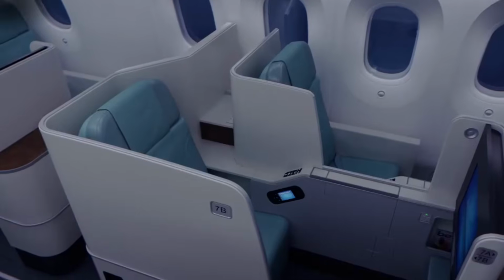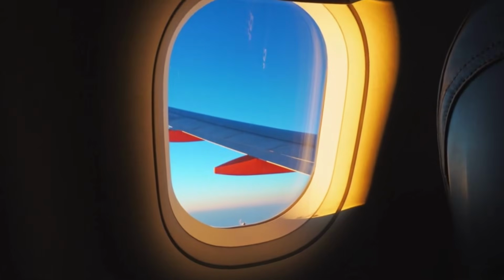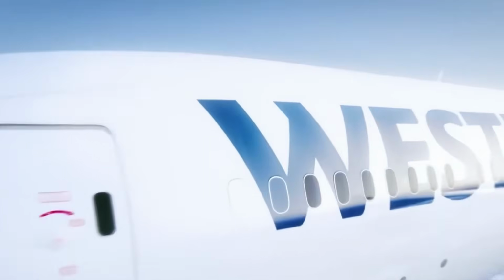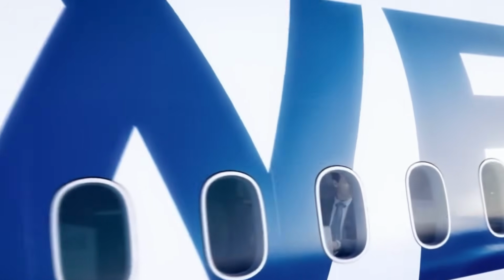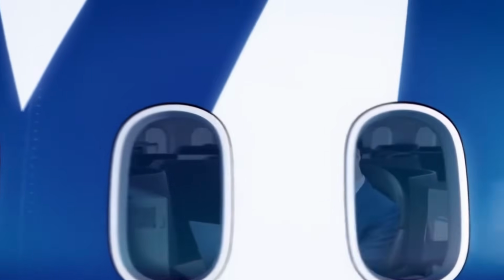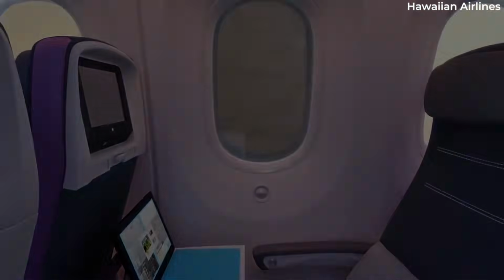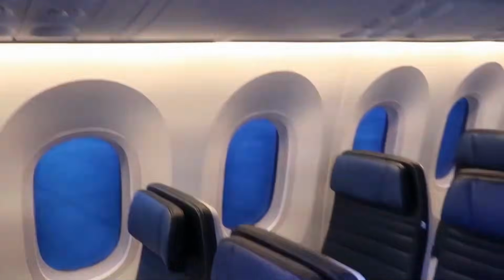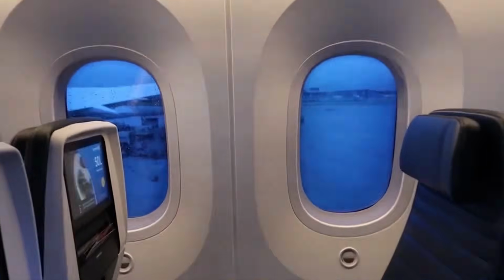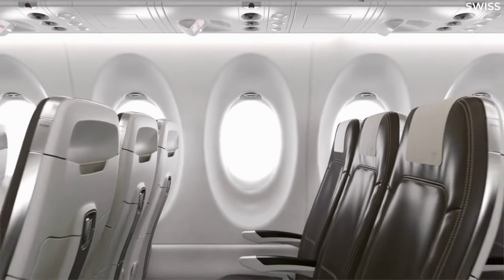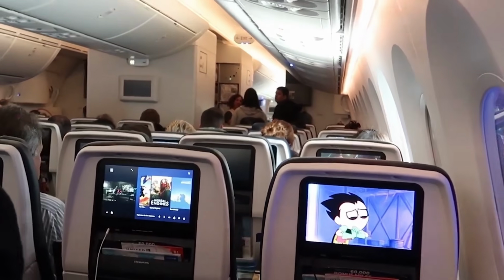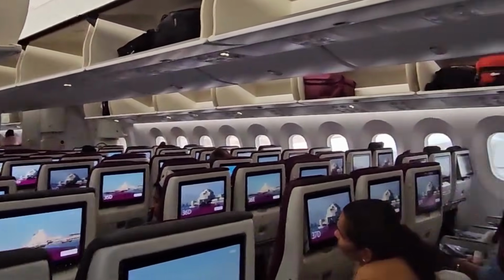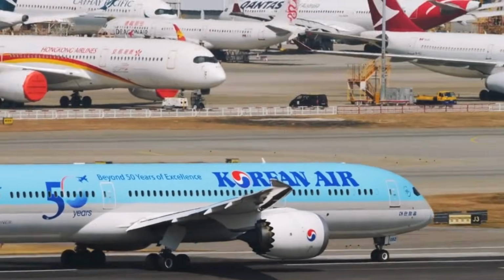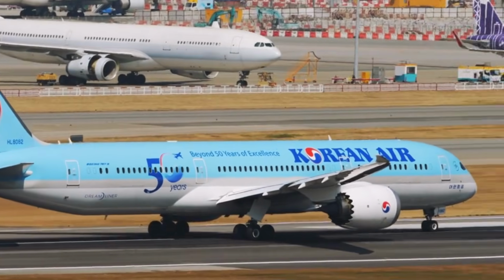The 787 window compared to windows of equivalent aluminum airliners is absolutely massive. In aircraft made primarily from aluminum, having holes this large in metal panels would result in the buildup of stress at window boundaries. As stress contours deviate around the window, this stress does not exceed material strength. But over repeated pressure cycles, tiny imperfections in the metal can grow into larger cracks and eventually fail. Holes this large in an aluminum airliner would severely shorten the plane's flying career before it needed fixing or disposal. But it is not a problem for the 787, thanks to composites' relative immunity to fatigue.